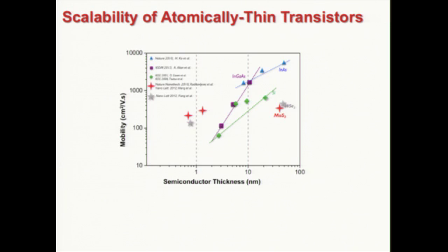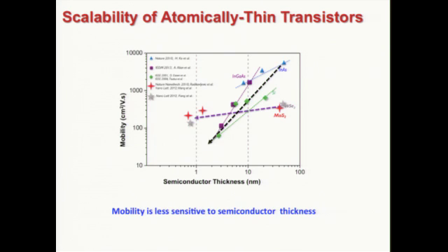About mobility, which is very crucial in device performance, as you see in this graph, even high mobility semiconductors such as indium gallium arsenide or indium arsenide lose mobility when we scale down the channel to a few nanometers. Actually, in indium gallium arsenide, the mobility goes below 100 square centimeter per volt second if it is thinned down to just 3 nanometers. And if we continue that, I would say at 1 nanometer, we will not be able to measure any mobility.